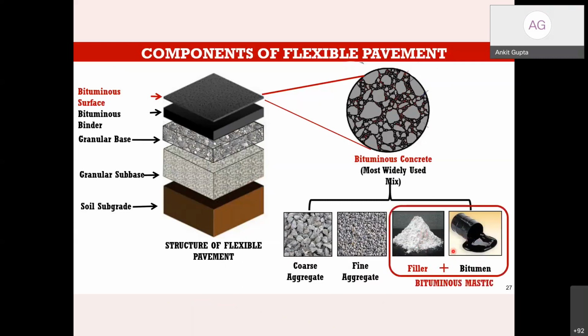Okay, it mixes with the bitumen and it becomes a thick kind of mastic, which is used for covering the aggregate surfaces. So the aggregate surfaces which are being covered by a black layer are not only of binder, it is basically a mix of bitumen plus filler, which is known as a bitumen mastic. Okay, but while interacting with this bitumen, this filler should be inert in nature. There should not be any chemical interaction with the bitumen. Okay, so this is the ideology behind the use of a filler.